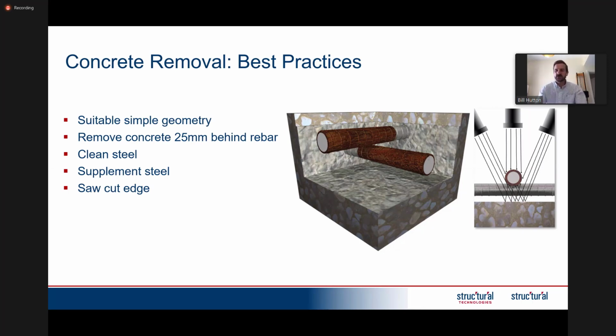And then also it's important that you have a saw cut, typically 10 to 12 millimeters, around the top of the repair area, and that prevents any feathered edges. So it means that you have a good secure bond at the top of your repair. And then sometimes this should also be roughened just to make sure you get that good lock and key.